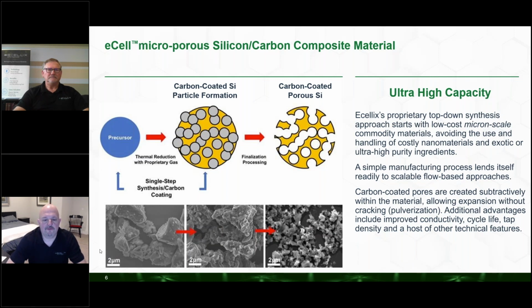Now that structure on the right is very important. What it allows is very, very small particle sizes that can expand and contract without breaking. And at the same time, those particles are coated with carbon. And that carbon prevents the material from reacting with the electrolyte. It prevents those surface reactions which harm a battery. By making this all in a single process, we're able to use very low quality, inexpensive, off-the-shelf components, and we're able to drive to a material that simply works.